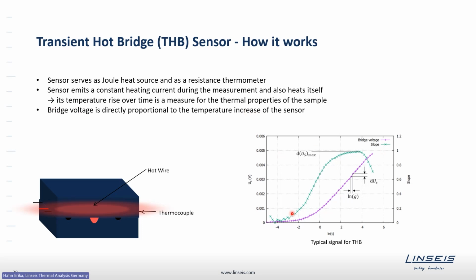Here you can see a typical signal of a THB sensor, where in purple you see the bridge voltage rising with time. For the evaluation, we look at the slope of the bridge voltage to find the maximum, which is the point where we extract the thermal conductivity. The decay afterwards is an indicator for the thermal diffusivity of the material.